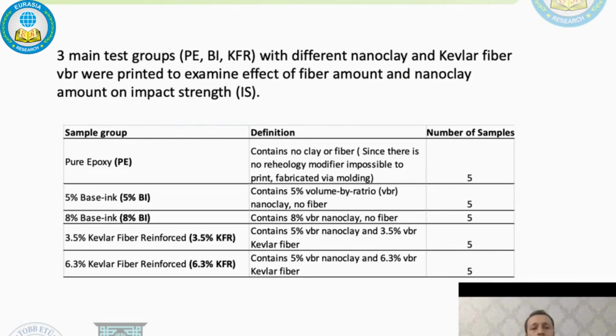three main test groups with different nanoclay and Kevlar fiber amounts were printed. First group is pure epoxy. The pure epoxy group contains no nanoclay or fiber. Since there is no rheology modifier, that ink is impossible to print. So all the pure epoxy samples were fabricated via molding.